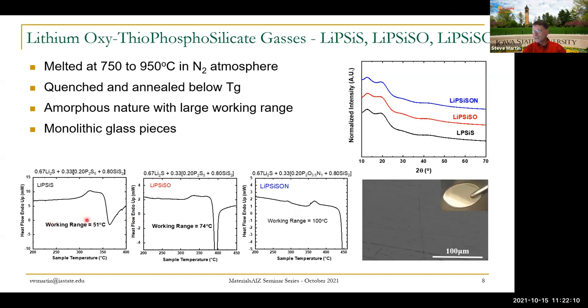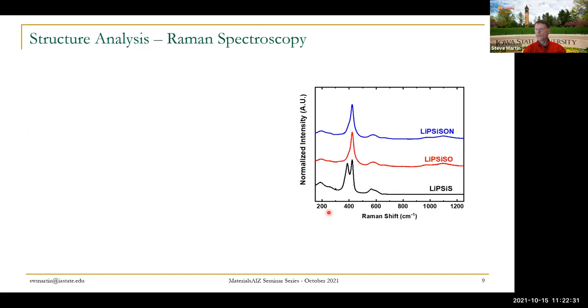So these glasses improve in their resistance to crystallization, and we get about a 100 degree working range. And that's what we've found is about the minimum we need for processability. I'll show you some more detailed crystallization studies in a moment, but at least this gives us a way to proof test the glasses and move on further.